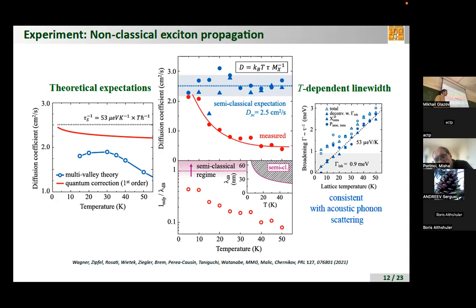Excitons, however, are bosons. Actually, the Berry phase in this particular situation is 2 pi. It doesn't mean that spin doesn't affect the interference. It affects the prefactor by about a factor of 2 in the best case. But at least if you study the diffusion of unpolarized particles, it will not change the regime of transport dramatically. It will still be weak localization. We have analyzed this a little bit, and we do not see a way how including spin may strongly change this result.